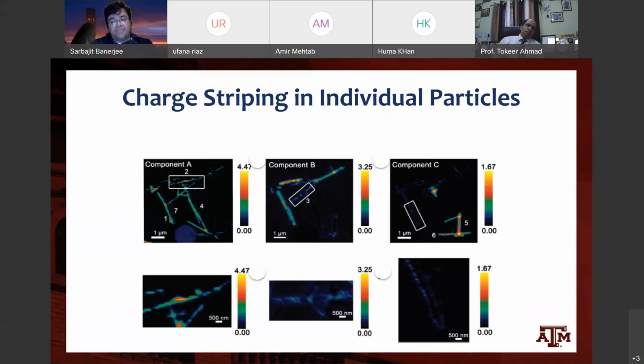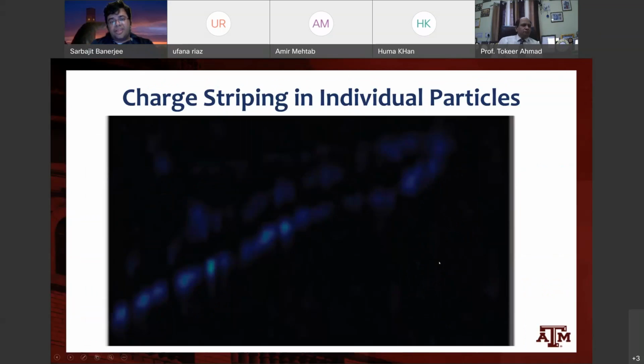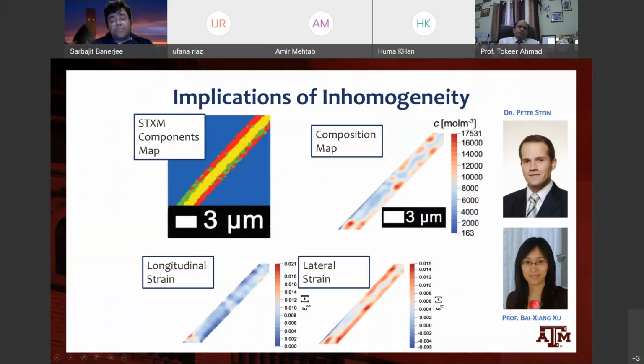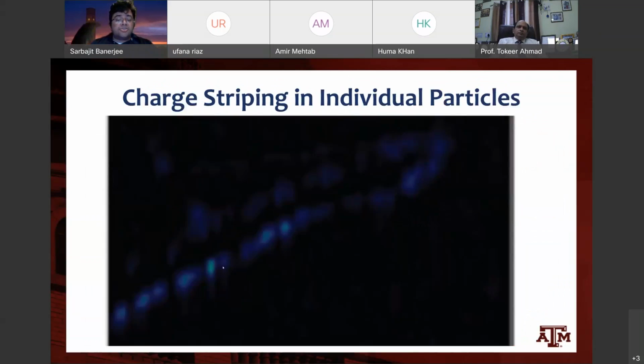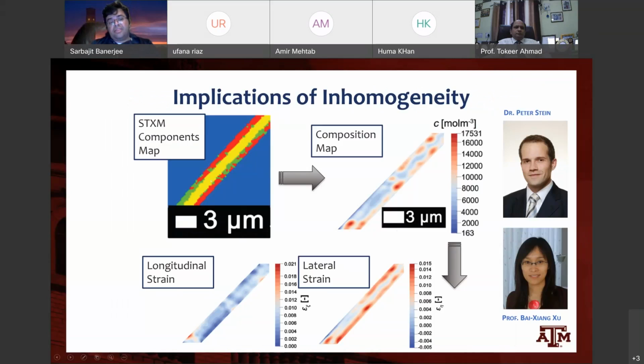Okay, and one of the cool things that we were able to image are phenomena like you see here of charge striping, right? So stripes being formed within individual particles. So what are the implications of this? The charge striping corresponds to lithium and no lithium. So you have these domains, and within individual particles you get these gradients in lithiation. Now these gradients mean, again, we saw that lithiation causes a change in lattice volume, and so local changes in lattice volume then result in longitudinal and lateral strain.